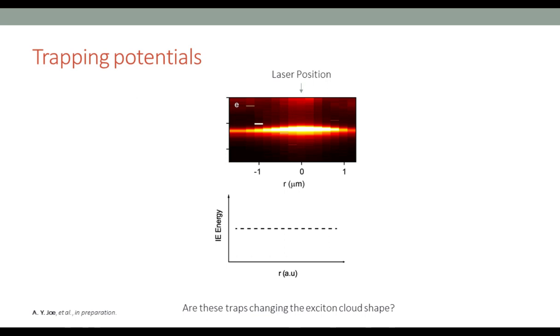Now, if we lower the outer gates, what you can see is that the outside energies drop down, but the energy in the center region remains at around 1.35, what it was when it was flat. You can also see that it's much darker, which is expected when you make an anti-trap type of shape. Now, if you do the opposite and raise the outer gates, we see the outer energy goes up, but we also see a brightening and still a lower energy in the center wire gate region. So we can demonstrate that we can generate different electrostatic profiles across our sample.